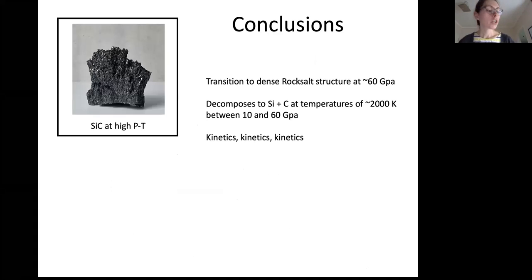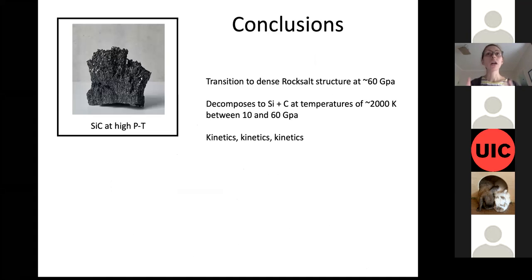Right, so conclusions from the pure silicon carbide system. We find that it transitions to a dense rock salt cubic structure, and that this happens at around 60 GPa. And that silicon carbide decomposes, or carbon begins to come out of the silicon carbide system, at temperatures of around 2000 degrees Kelvin when you're between 10 and 60 GPa in our experiments.